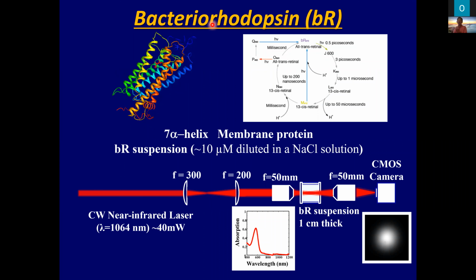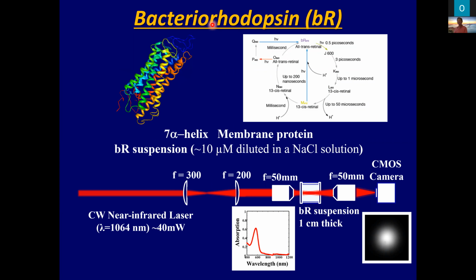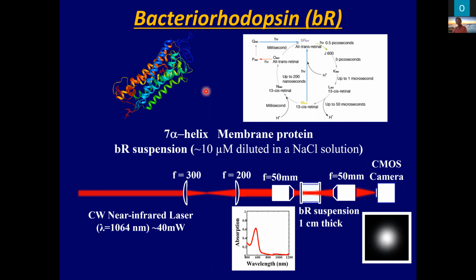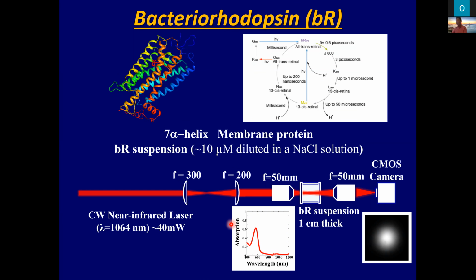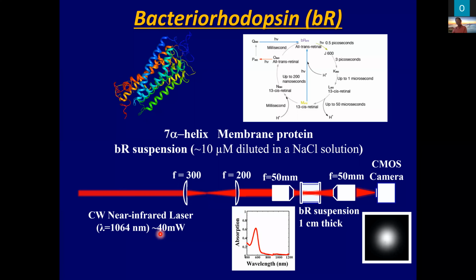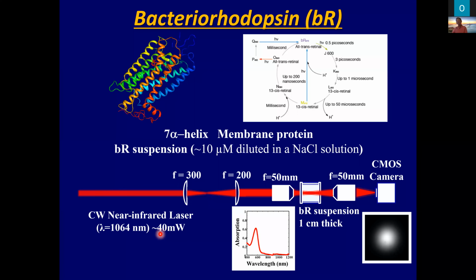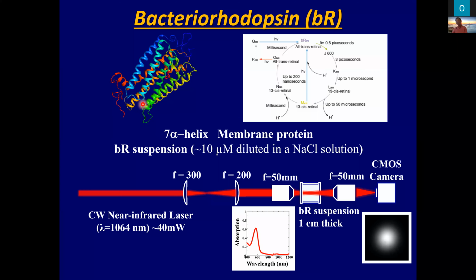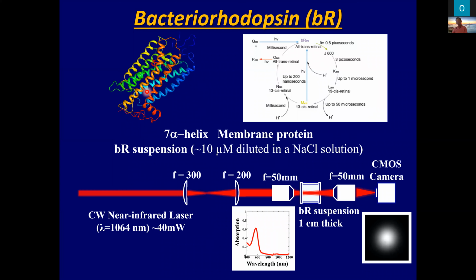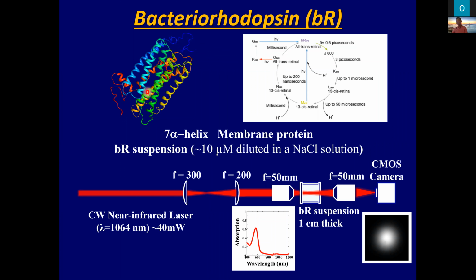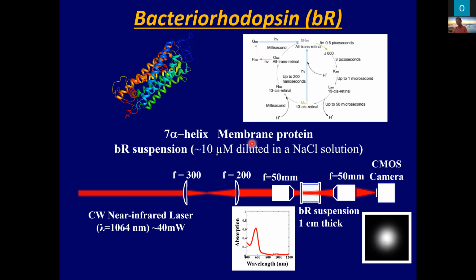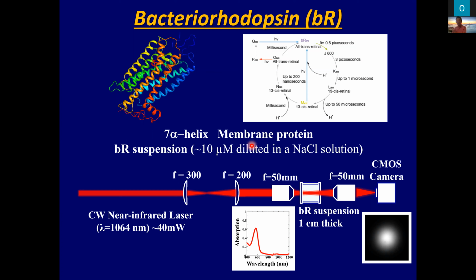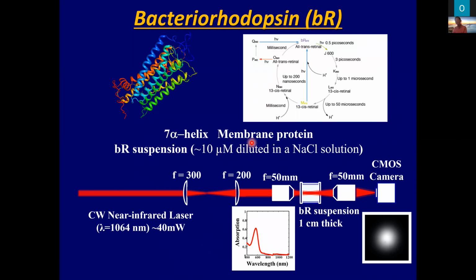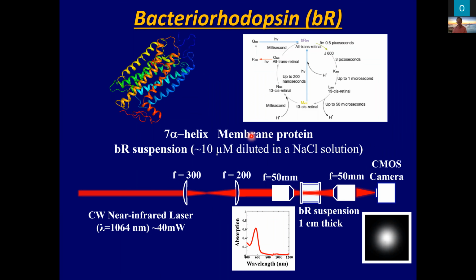To avoid photobleaching of this bacteriorhodopsin, we use 1 micron near-infrared light sources. In this way, we can fully compensate the thermal effect of the bacteriorhodopsin itself. And we also utilize the solvent D2O instead of H2O, so we can fully suppress the thermal issue inside the bacteriorhodopsin suspension.